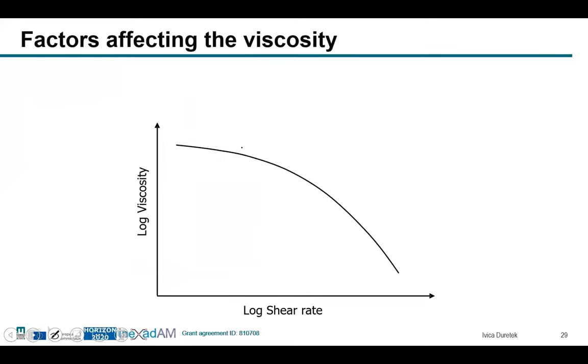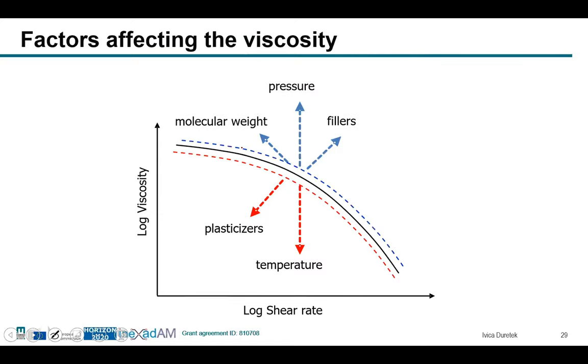Viscosity is affected by many factors. For example, plasticizer and temperature decrease the viscosity. This means with increasing temperature, viscosity will be lower. With increasing pressure, the viscosity increases, and increasing molecular weight increases the viscosity too. And if we add fillers like fibers or metal or ceramic particles, with increasing filler loading, the viscosity increases too.